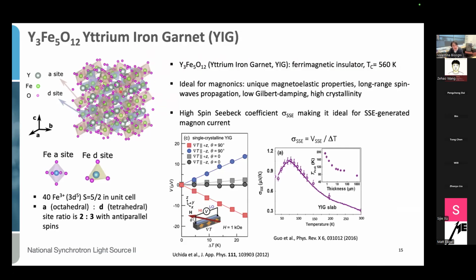containing 40 iron atoms. So all the iron atoms are in the same oxidation state, and they have a spin 5/2, but they are coordinated into 2 different oxygen cages. So we can have the octahedral site and we can have the tetrahedral site. And the interesting point is that the spin in this different configuration is aligned in opposite ways. And because the occupation ratio of the octahedral and tetrahedral site is not 1:1, but is 2:3, this essentially is the cause of the residual ferrimagnetism in this material.